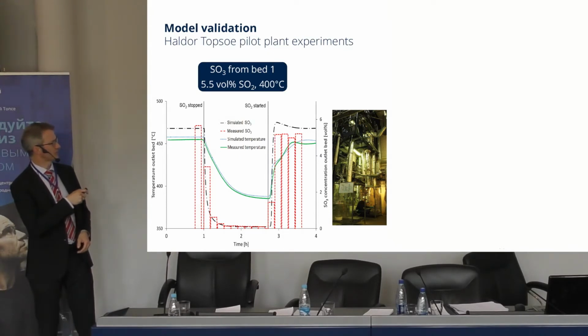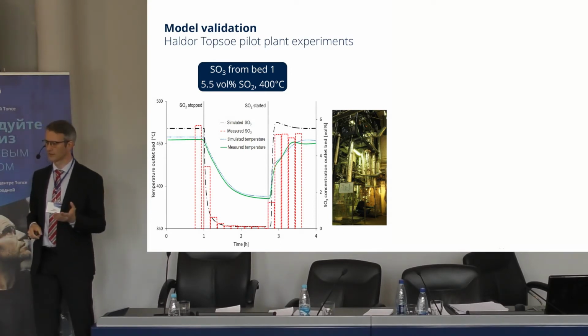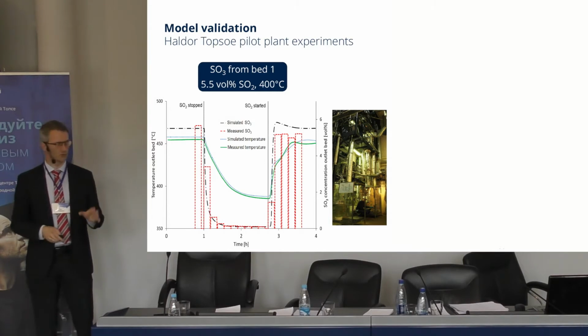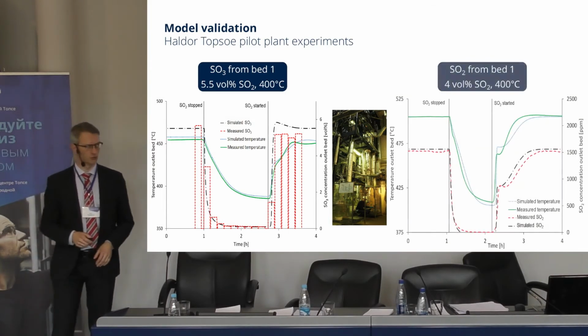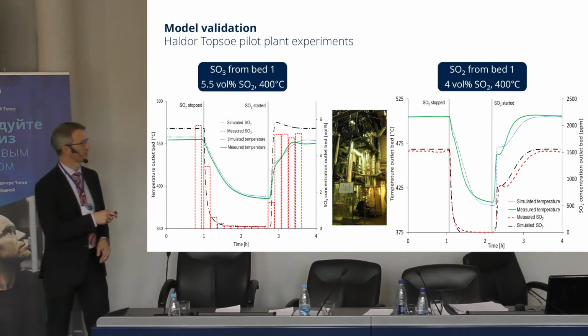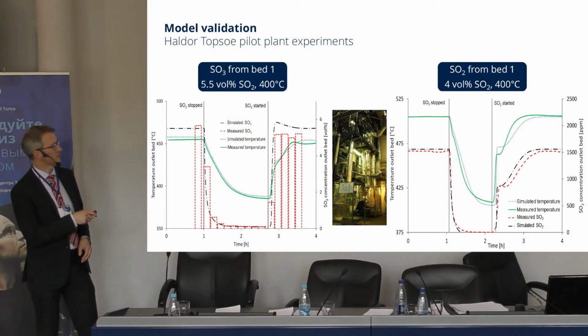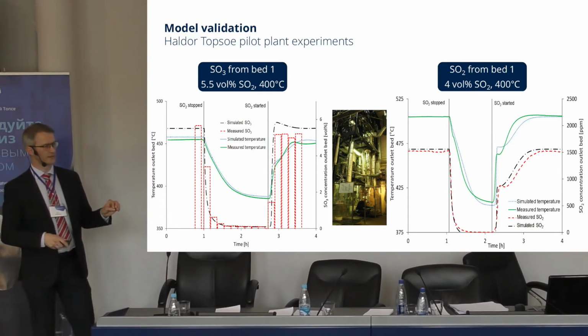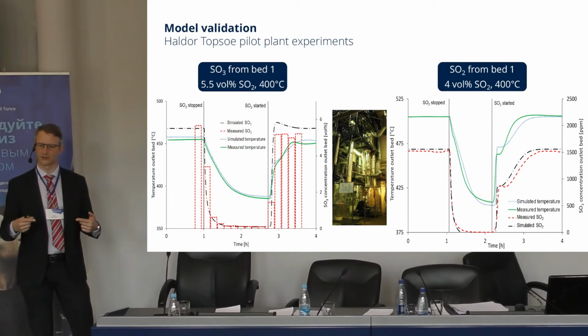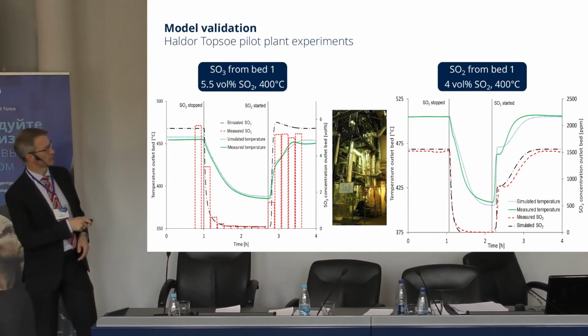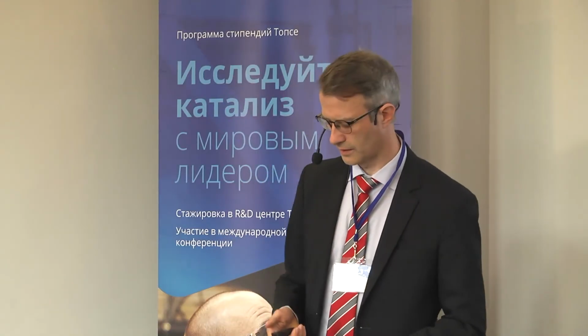You can also see there's a tailing of the SO3 coming off bed one, the red one, that's the measured, and the black one is the calculated curve. And we can do that quite well. The same goes for SO2 on the right. A similar experiment, we shut off the SO2 feed here, and then we look at temperature, goes down, goes up, and you can see there's a small bump on the curve here. That's due to the exothermic uptake of the SO3 that will create a small heat wave in this case. That's also captured by the model. And we can see that the SO2 emissions shown by the red and black are also well modeled for the pilot.